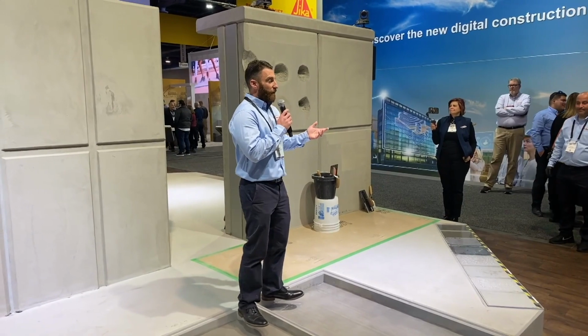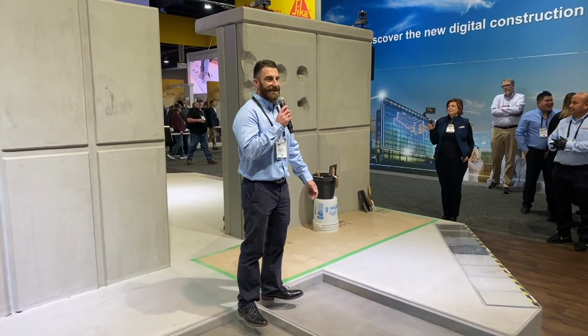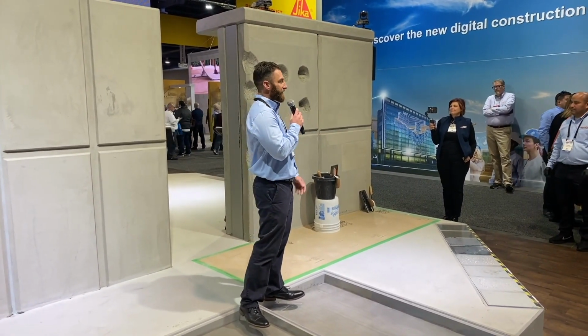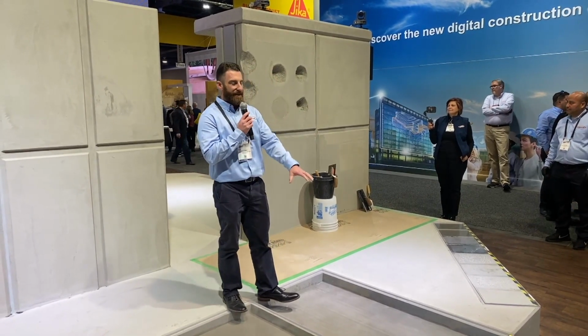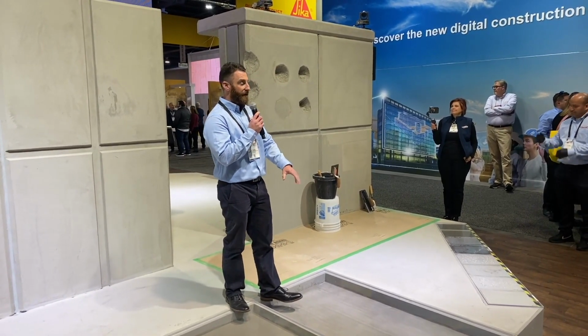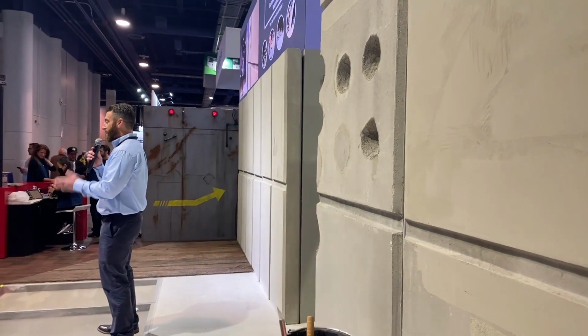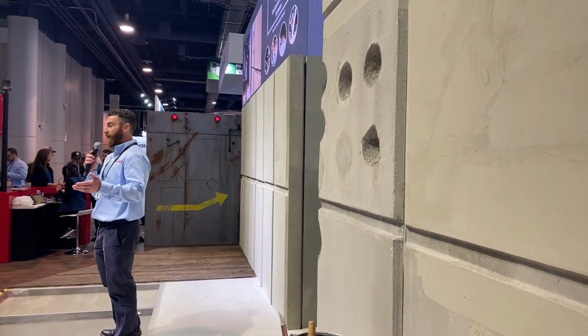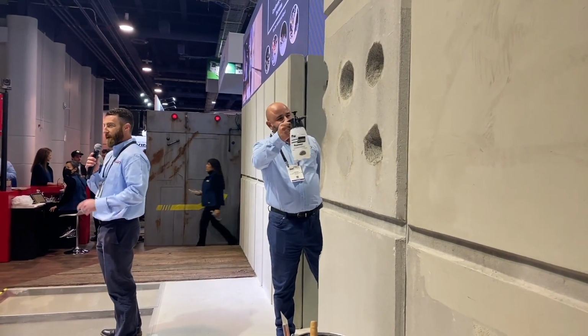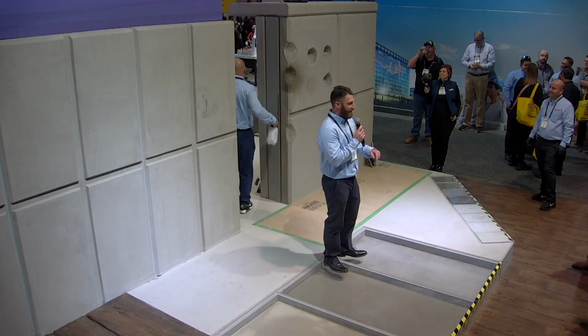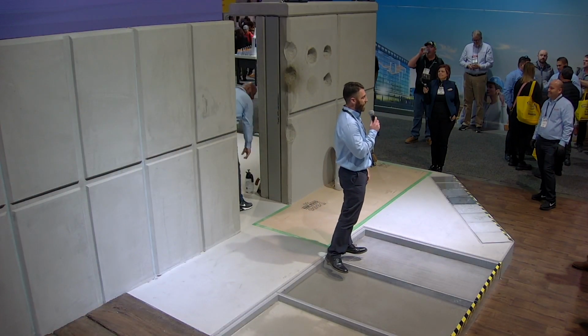For example, we placed RapidSet cement concrete at SeaTac Airport back in the mid-90s. We've had independent labs come and check the in-place concrete multiple times over the years. And they found not only does the strength continue to increase well beyond the 28-day strength, but the flexural strength today is actually double what it was when they first started landing planes on it.